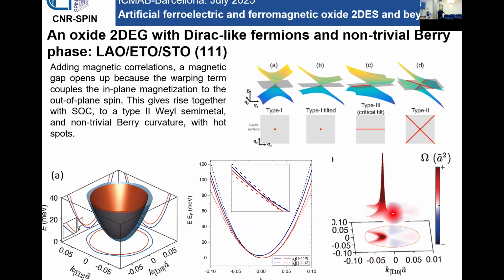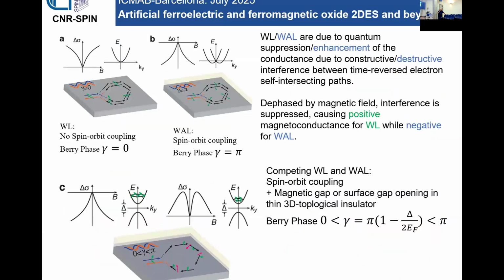You get hot spots in the Berry curvature, and this corresponds to a non-trivial Berry phase, which is neither zero nor pi. And what is interesting is that there is a very easy consequence of this non-trivial Berry phase that you can measure by performing a magnetoconductance measurement at low temperature. Measure the magnetoresistance or the magnetoconductance as a function of the magnetic field. In a standard two-dimensional electron gas or in a metal without spin-orbit coupling, you expect the Berry phase is either 0 or pi. When it's 0, you usually have the weak localization mechanism for change of magnetoconductance. When it's pi, you have a weak anti-localization quantum correction at low temperature.